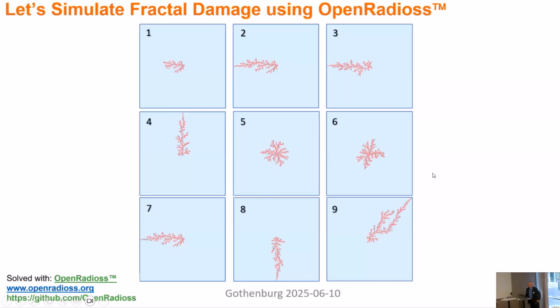And then we implemented it. So we coded it. First, I did it as a user subroutine to pre-damage the structure. This is not the failure criteria. So you apply a pre-damage, and then you apply your material model and your fracture criteria, whatever it is. It can be anything. But then you have a structure, for example on your windshield or glass. So this is a large glass piece, and the small pieces are the FE, finite elements. So it's a very fine mesh, but whatever, it can be the size of this window here or the size of a smartphone or whatever, with a lot of elements.